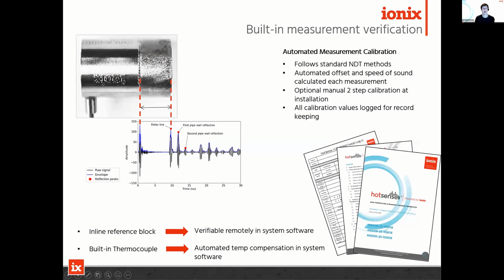I mentioned the validation of the measurements. The front section of the probe is a delay line, and what it means is that with every measurement you get a reference point from which you can take your thickness readings. It's really useful as well just to see once it's installed. I'm not sure of your UT experience, but by looking at the ratios and the amplitudes of these peaks and their relative ratios to each other, we can gain information about not only what's going on with the transducer, but also extra information about what's going on in the pipe other than just the change in thickness, for example.